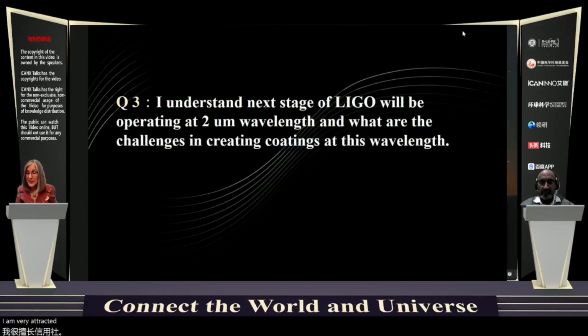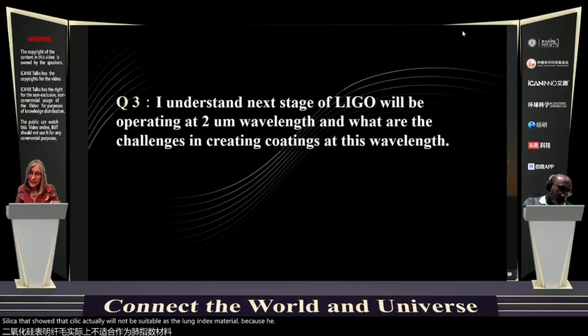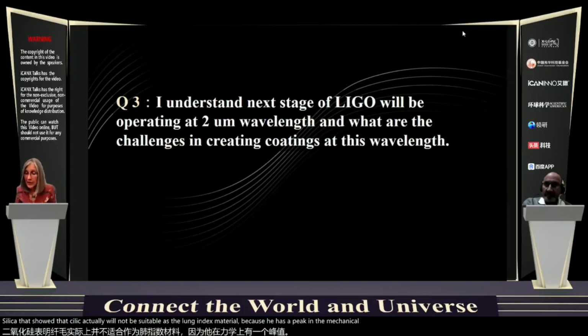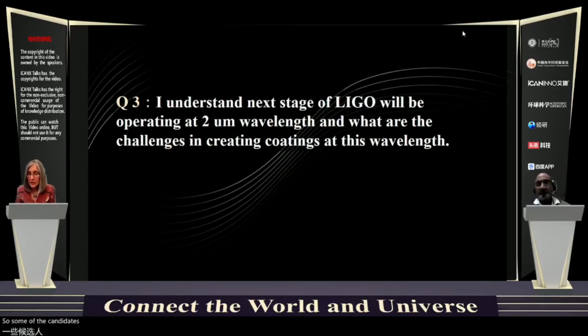we are going to start looking into mechanical loss of the oxides at cryogenic temperatures. And I can tell you, there are preliminary results on pure silica that show that silica will not be suitable as a low index material because it has a peak in the mechanical loss at cryogenic temperatures. So some of the candidates that are being looked at are, for example, amorphous silicon.